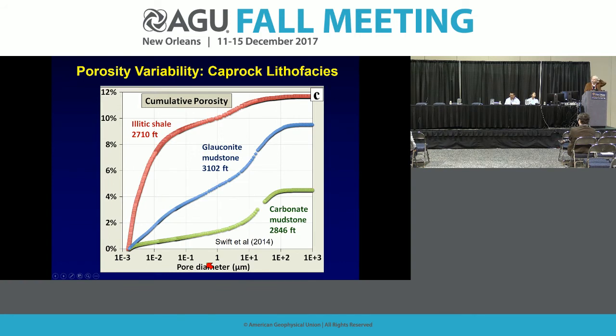So just to give an example of how neutron scattering is used to look at a particular mudstone, this is the Eau Claire, which Anastasia referred to. This is a very regional caprock in the central part of the United States. And here we see three kinds of outcomes, depending on which lithofacies you're in within this large caprock setting. We have an illitic shale, with a high percentage of nanopores. We have 1 nanometer right here, 10 nanometers, 100 nanometers. Then we look at somewhat different lithofacies, glauconite-rich versus carbonate-rich. We get different distributions, different kinds of behavior.